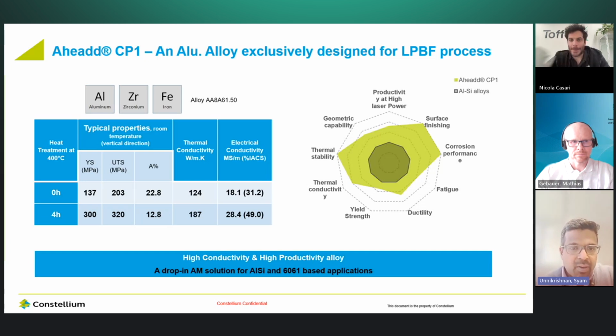So in the table, you can see the mechanical properties of this particular alloy. Contrary to aluminum silicon alloys, at 0 hours, that means as built without heat treatment at 400 degrees Celsius, the alloy is really soft, at 137 MPa, with more than 20% elongation and low thermal conductivity. But when we do a heat treatment of 400 degrees Celsius for 4 hours, the mechanical properties increase up to 300 MPa yield strength and more than 10% elongation, whereas the thermal conductivity and electrical conductivity go up.